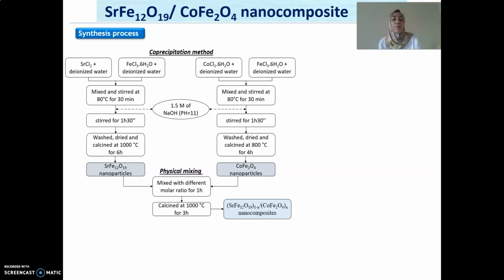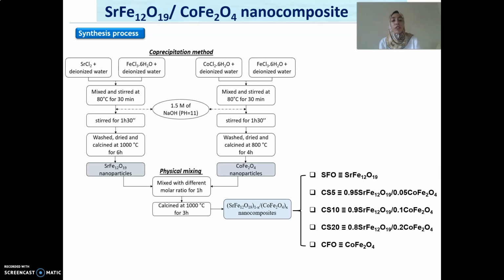To prepare our nanocomposites, we start by preparing the strontium hexaferrite and cobalt spinel ferrite nanoparticles by using the standard co-precipitation method. Then the prepared nanoparticles were mixed physically using an agate mortar for 1 hour and then calcined at 1000 degrees Celsius for 3 hours to achieve strontium hexaferrite, cobalt spinel ferrite nanocomposites with different molar ratios. For the rest of this presentation, we will refer to the parent strontium hexaferrite and cobalt spinel ferrite as SFO and CFO, while we will use CS5, CS10, and CS20 to refer to the nanocomposites with 5%, 10%, and 20% of the soft phase.